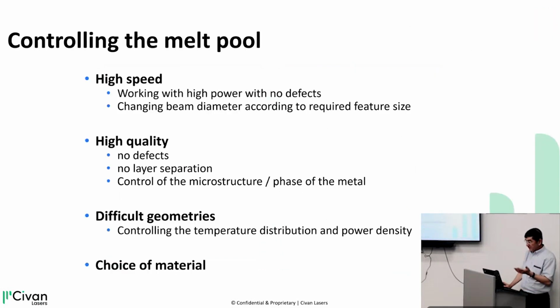So first of all, in terms of controlling the melt pool, you can increase the speed because you control what's happening there. Today, if you put too much power into the powder bed, the grains just fly away. You create thermal currents and all kinds of sputter. It's easy to get a kilowatt single mode laser, but if you put it on the powder bed, the grains are just going to fly. By controlling what's happening there, we can make it much faster, higher quality, with difficult geometries and different materials.